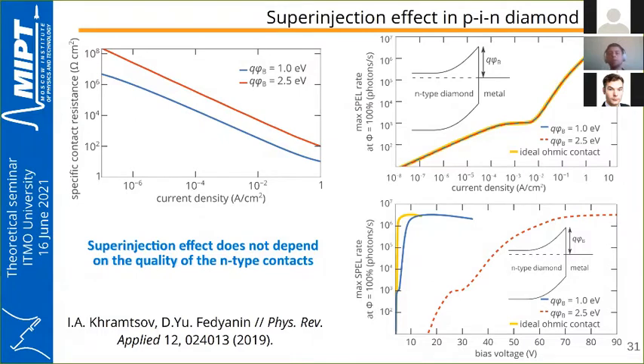It was also found that the superinjection effect can be observed even with poor contacts to the N-type diamond, since in the diamond community it's well known that contacts to N-type diamond are very poor, characterized by high contact resistance. But it can be seen from this plot that the dependence of the maximum SPL rate on current density stays the same for different contacts - it doesn't depend on the type of contact. It's the same for the ideal ohmic contact and for the bad Schottky contact with a barrier height of 2.5 electron volts.